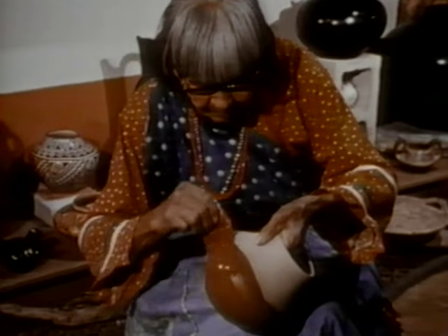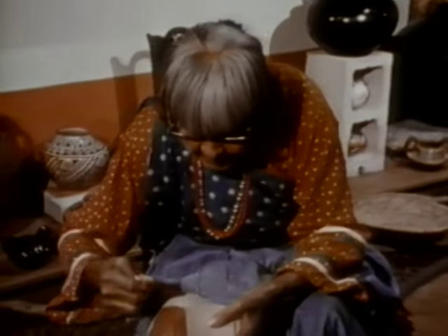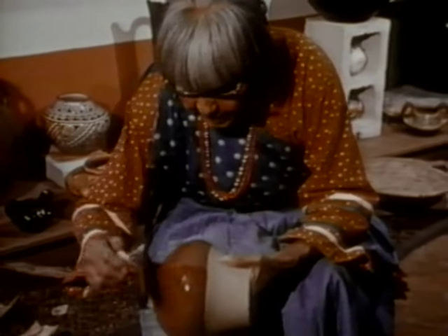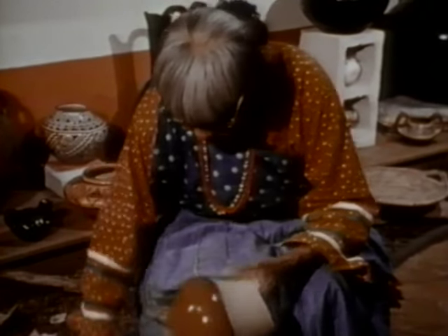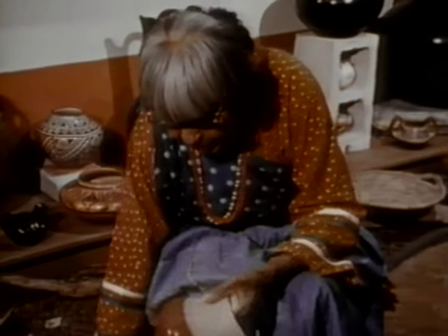An earth-colored clay in semi-liquid form, called a slip, is applied. Four or five coats are used, and only as much area is covered as can be polished before the slip dries completely. Should the slip dry before polishing is completed, streaks will show up after the firing.